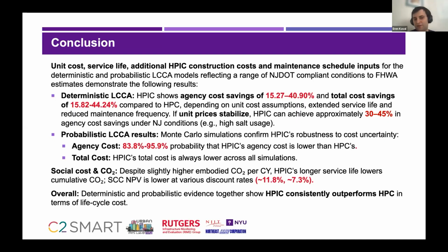And additionally, the probabilistic LCCA analysis done by Monte Carlo simulations confirmed that HPIC is robust to cost uncertainty, where there is around an 84 to 96% probability that the HPIC agency cost is going to be lower than its compared alternative, HPC, for life cycle cost analysis values. And the total cost of HPIC is always going to be lower based on the simulations that were done.